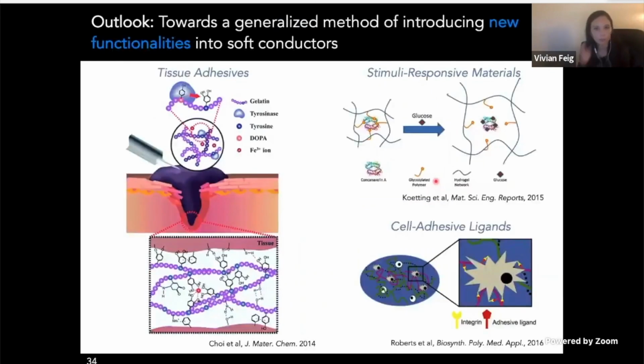So ultimately, I think that the main advantage of this kind of interpenetrating network approach is that it allows us to take advantage of all of the exciting developments that are happening in the field of hydrogel materials. Because moving forward, we can imagine replacing that polyacrylic acid network with other networks that exhibit different functional properties beyond stretchability. So here's where I really think that there are exciting opportunities for chemists to think about what sort of new functionalities might be important at the bioelectronic interface.